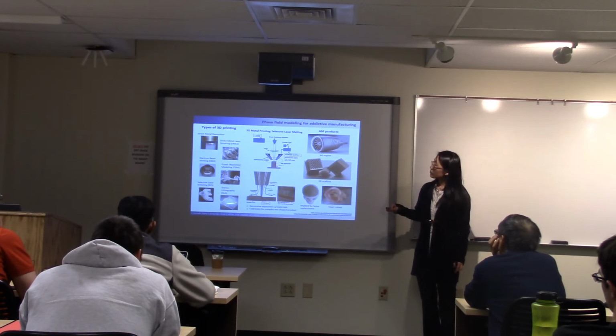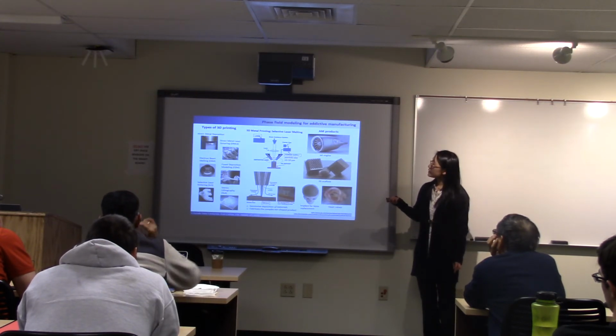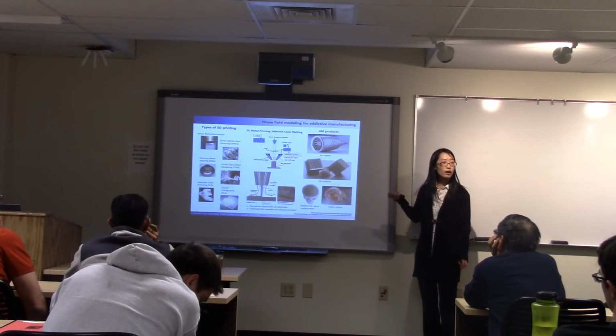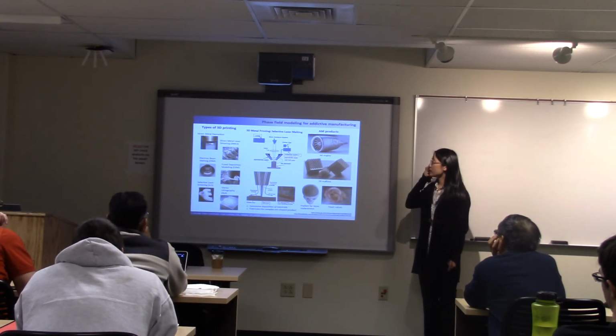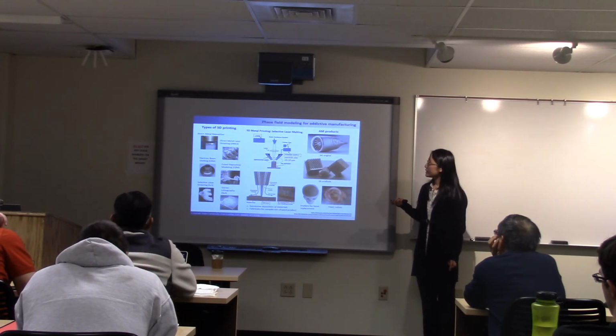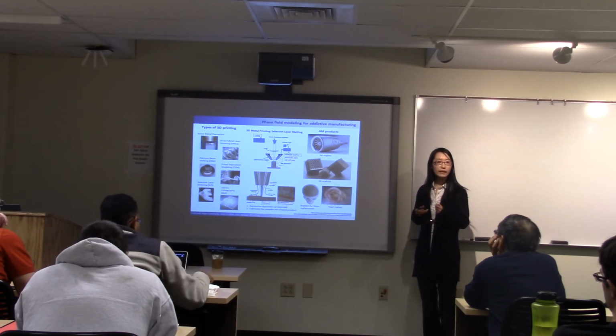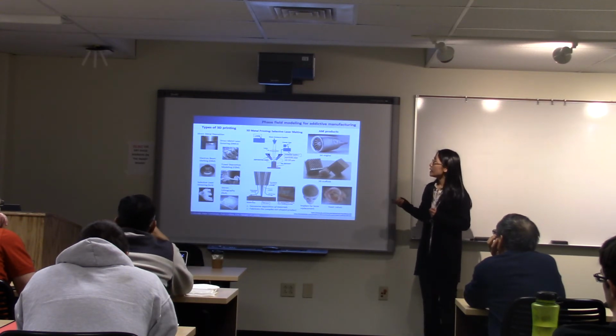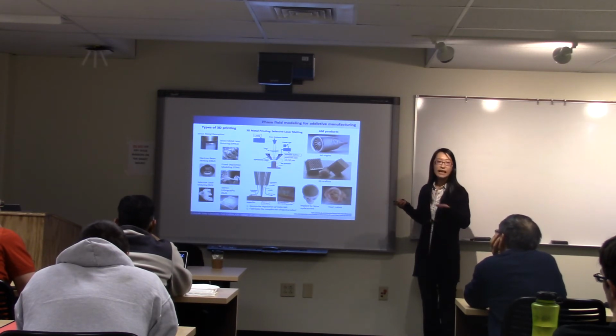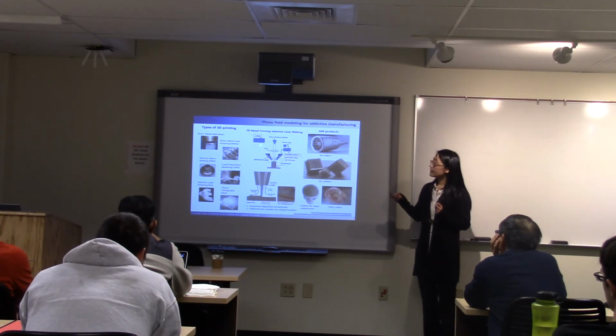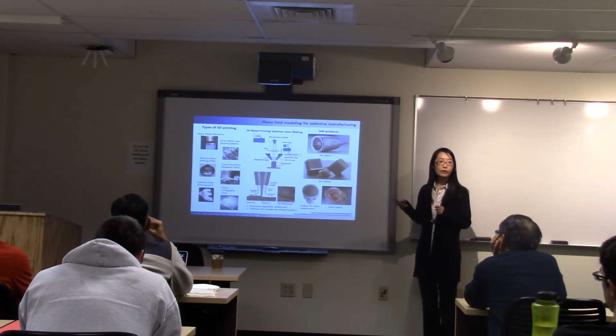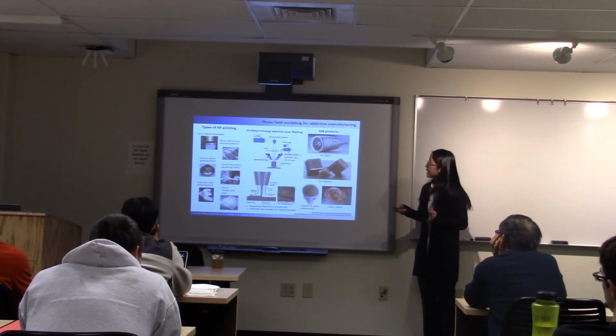And here are some types of 3D printing, and I also show a figure for 3D metal printing in selective laser melting, which our modeling is mainly based on at this point. So in selective laser melting of metal, a thin slice of metal powder is selectively melted by a high power laser beam to make the 2D slice of the part geometry. And this whole process happens in a chamber containing a tightly controlled atmosphere of inert gas.